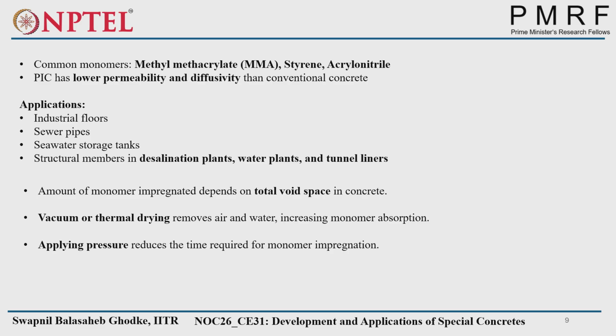So amount of monomer impregnated depends on the total void space in concrete. Obviously, whatever the void space available, that amount of monomer will only be occupied by the concrete. Vacuum or thermal drying removes air and water, increasing monomer absorption. Applying pressure reduces the time required for monomer impregnation. Higher the pressure, less time required. Lower the pressure, more time required to fully impregnate the monomer into the concrete voids.